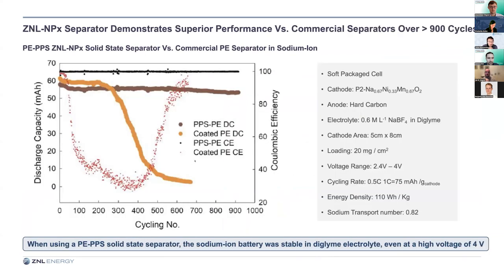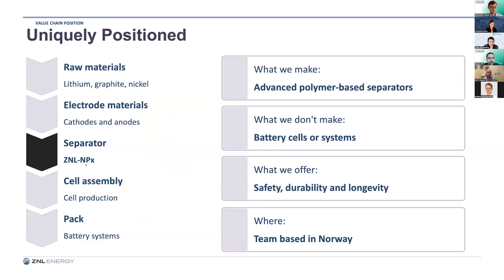We also have external tests. This is from a sodium cell with 4 volt. You see the orange and the scattered, that's the conventional separator. With ours it is almost at 100%, and it's really even on the cycling. So we lasted over 900 cycles. So this is on next level chemistry. We also see a similar test in high NMC 9XX from a US player where we doubled the lifetime of the battery.